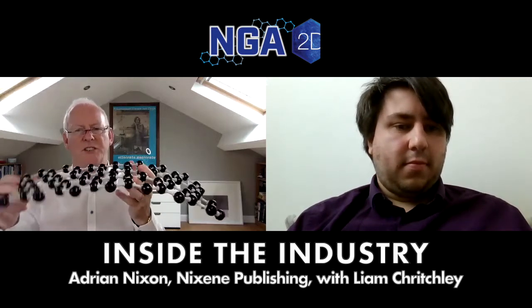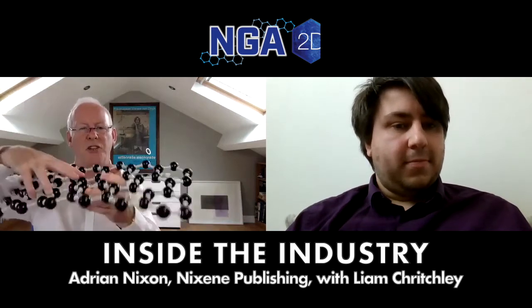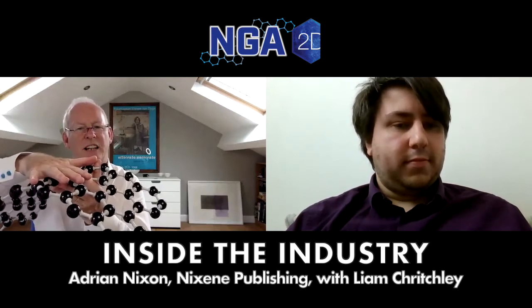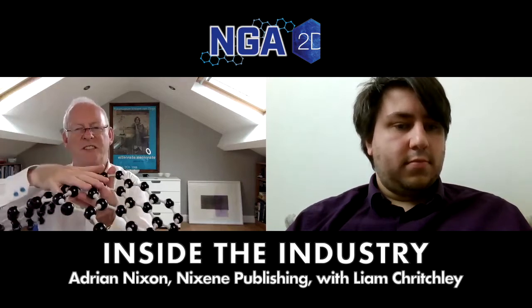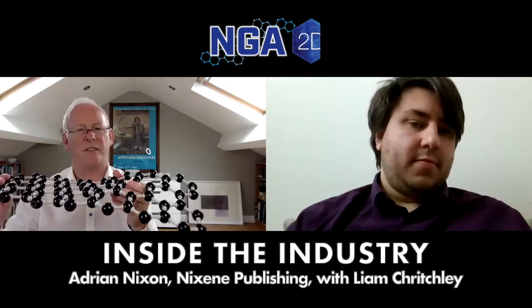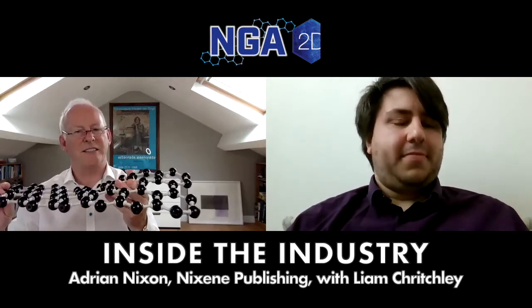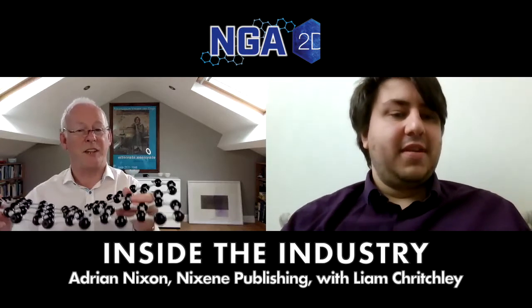But what researchers have found is that if you place one layer of graphene on top of another, so you've got bilayer graphene, and then you just twist it slightly, by roughly 1 degree, then all of a sudden the graphene starts to become a superconductor down at around 2 degrees Kelvin. That's really cold, minus 271 degrees centigrade. But the point is that nobody ever expected that, and nobody really knows why yet. They think it's connected with